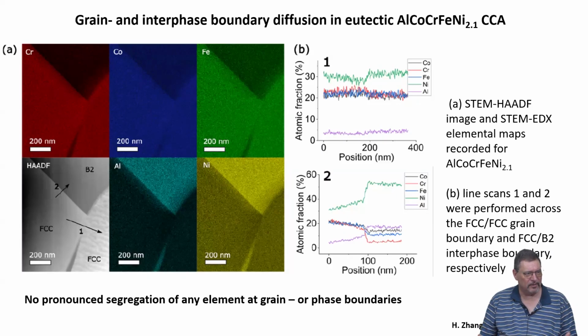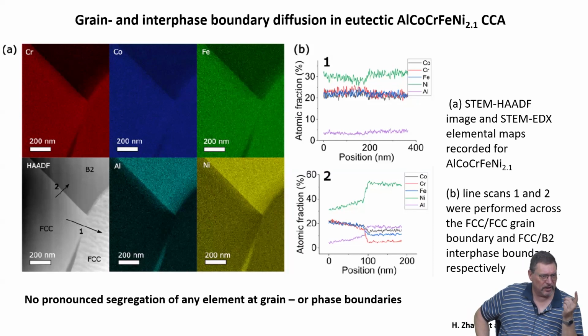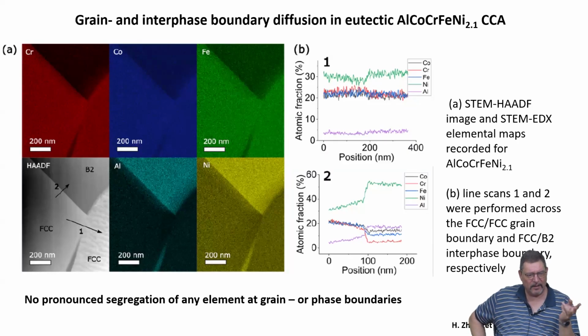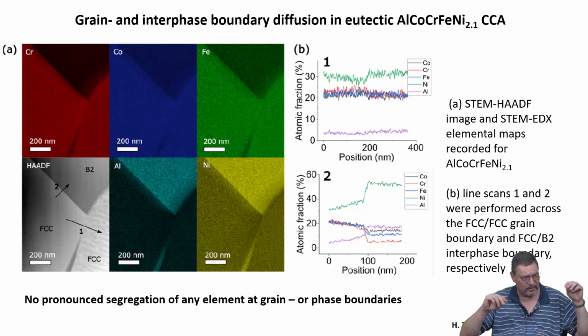Now, when you want to analyze the diffusion along internal interfaces in such a material, you need to worry about several different things. You need to worry about how much interface length per unit area is there for each of the type of interfaces. And you need to also worry about how is the interconnectivity, the percolation of each type of interfaces. Because if we do not have a percolating, a fully interconnected pathway, then this does not contribute to really long-scale diffusion. And so it means we have now to analyze the microstructure in terms of also how much interface area is there and how much of these interfaces is interconnected.